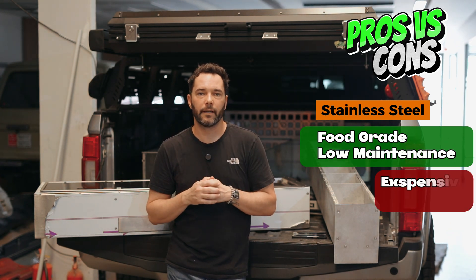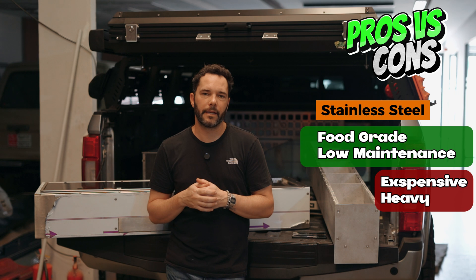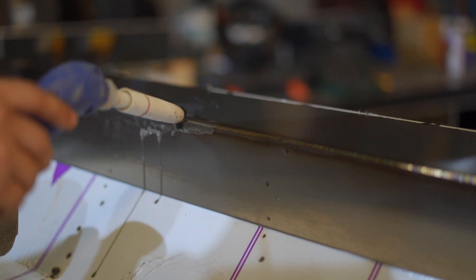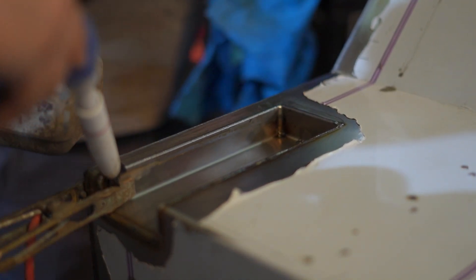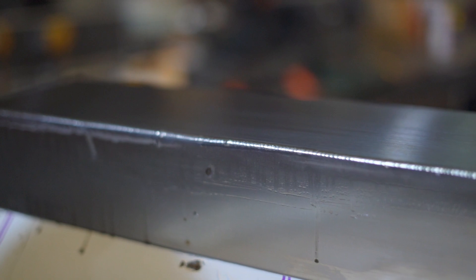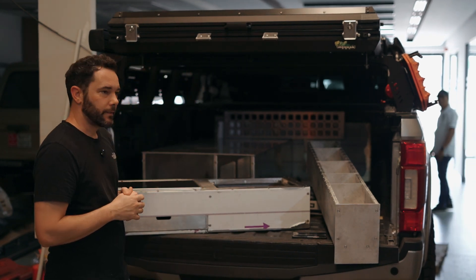For me, I didn't want any chemicals going into the tank. I wanted a stainless steel tank because it is inherently food grade. If you use a higher grade of stainless steel, there isn't any treatment needed to keep it food grade — with the exception of just regular maintenance and cleaning. One important thing for me was finding a shop that did electro brush cleaning or passivation. It's not strictly necessary for food grade, but passivation cleans the weld line and restores the chromium oxide layer on the weld, basically preserving that weld and preventing any rust. Even stainless steel can rust — just look at your barbecue outside. So that was an important layer of protection, especially since I'm not painting this tank. It's covered underneath my roller cover and behind a painted moly panel.